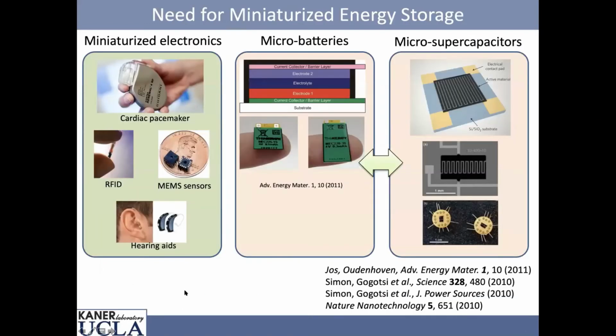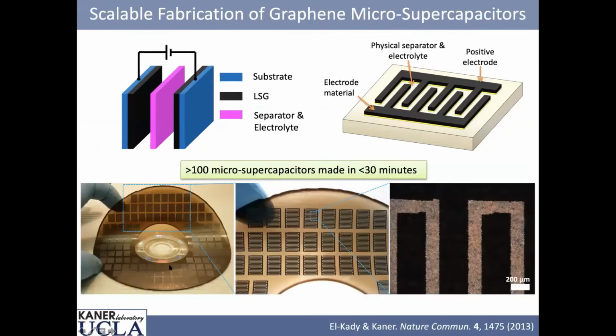All right, another thing that I wanted to show you is we can make miniature devices. And why do you want miniature devices? Well, if you have a pacemaker or a radio frequency device or a hearing aid, we need little tiny power sources. And so you can get micro batteries or you can get micro supercapacitors. We decided to just take these interdigitated designs from the literature and reproduce them. On one of our films, we just told the laser to make 100 different interdigitated electrodes. You can do this in about 20 or 30 minutes, and you can see you can do this pretty well.